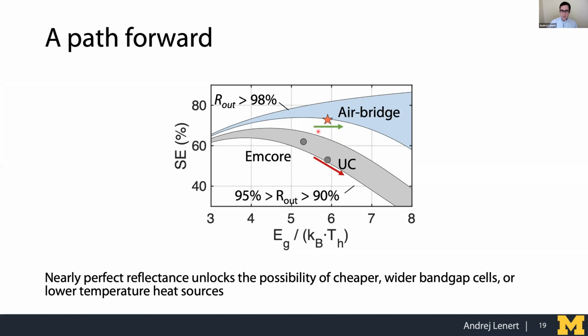And if we are in the conventional reflectance regime, as we increase band gap, we take a hit on spectral efficiency. But if we start to approach above 98 or 99% reflectance, which can be enabled by the air bridge architecture, we see that we enter a regime where we're much less sensitive to band gap and temperature. And so this opens up a very exciting possibility of using cheaper, wider band gap cells that have already been produced for solar applications, or enabling the use of lower temperature heat sources. And I think both of these are very exciting as a path forward for TPV technology. So I'll end there and turn it over to Jared.